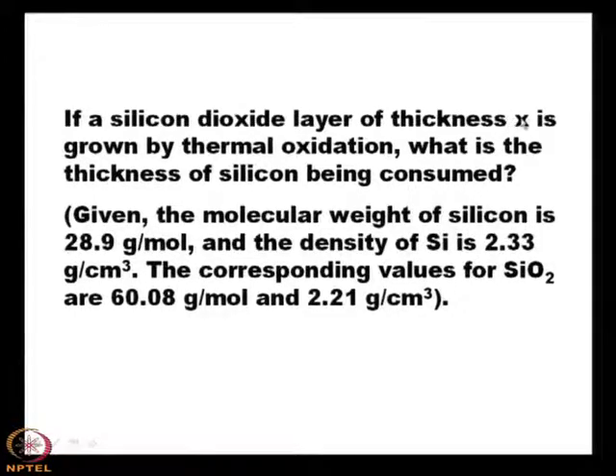So, if it is x, then how much thermal oxidation will be the silicon dioxide? If a silicon dioxide layer of thickness x is grown by thermal oxidation, what is the thickness of silicon being consumed? Given the molecular weight of silicon is 28.9 gram per mole and the density of silicon is 2.33 gram per centimeter cube, the corresponding values for SiO2 are 60.08 gram per mole and 2.21 gram per centimeter cube.